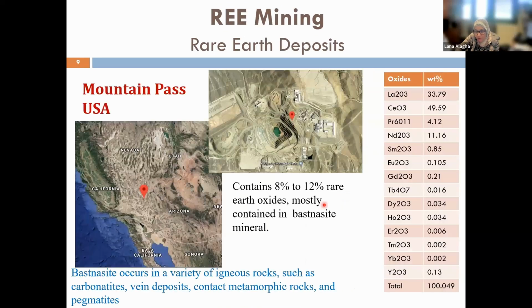So for the rare earth deposits, I will discuss 3 famous deposits. One of them is located in the USA, which is Mountain Pass, which usually contains 8 to 12% rare earth oxides, and the relative abundance of different rare earth oxides within this deposit is shown here. So lanthanum, for example, is about 33% of the rare earth oxide, and about 50% is cerium. So bastnäsite here contains more lighter rare earth elements than heavier rare earth elements.